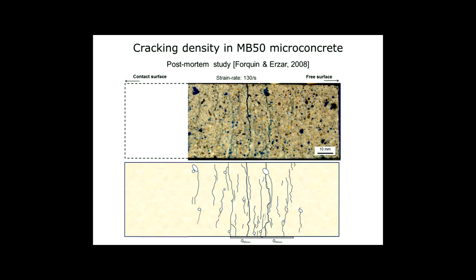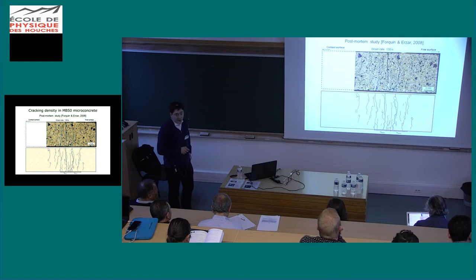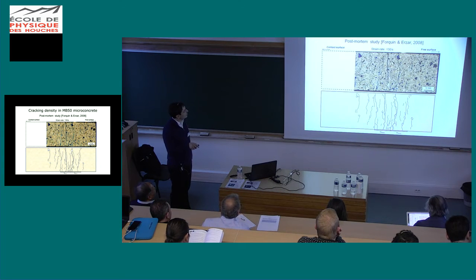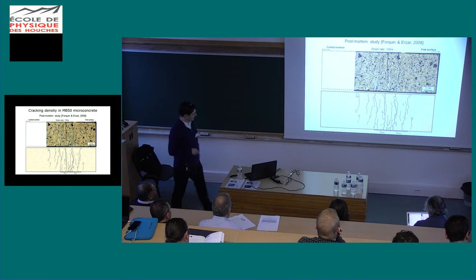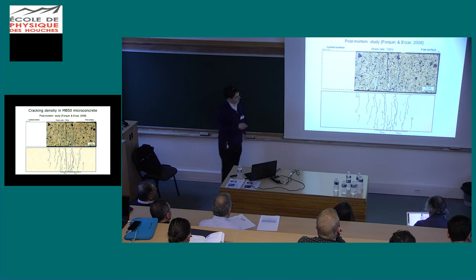And the second important point is the amount of cracks that is now observed. You can see in this microconcrete loaded at 130 second minus 1, the numerous cracks that were supposedly triggered on defects, on pores, and propagate dynamically in the whole sample.